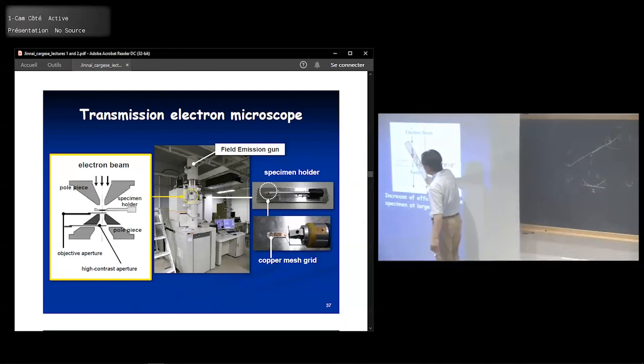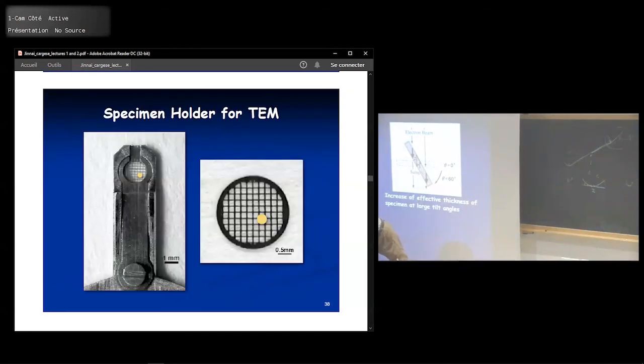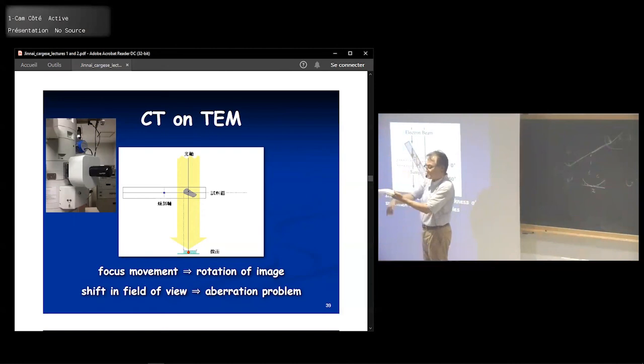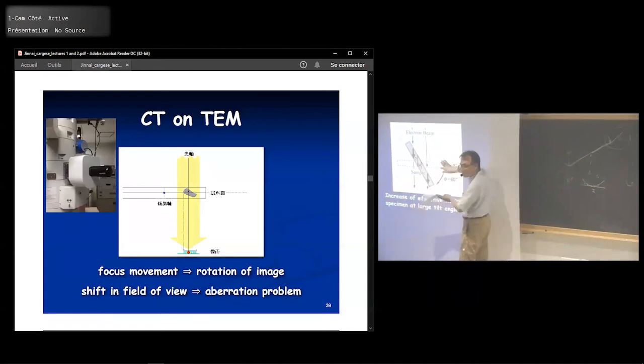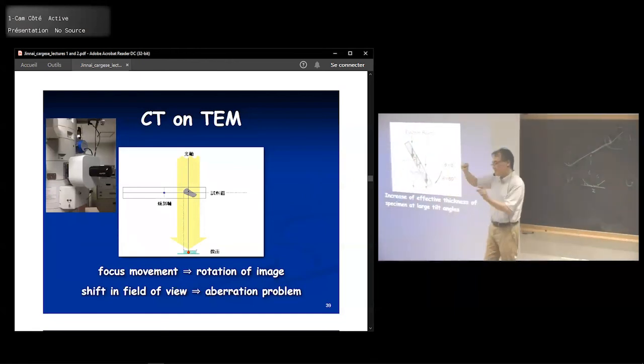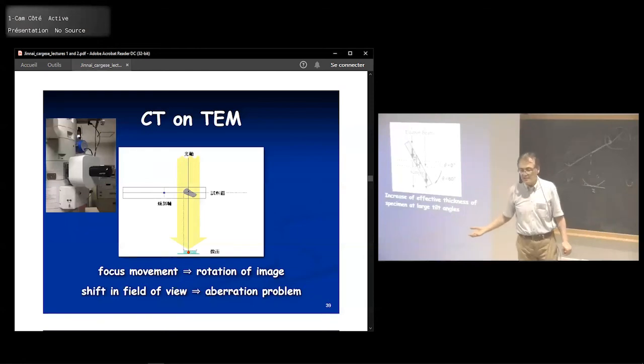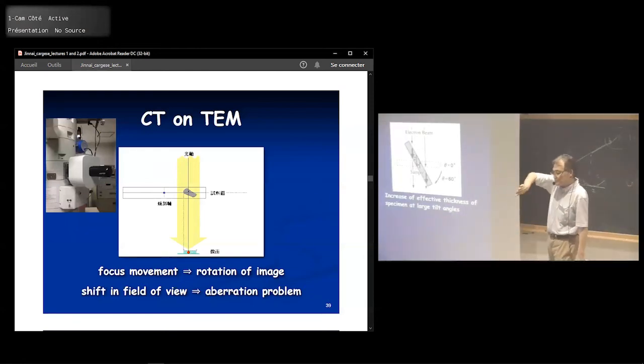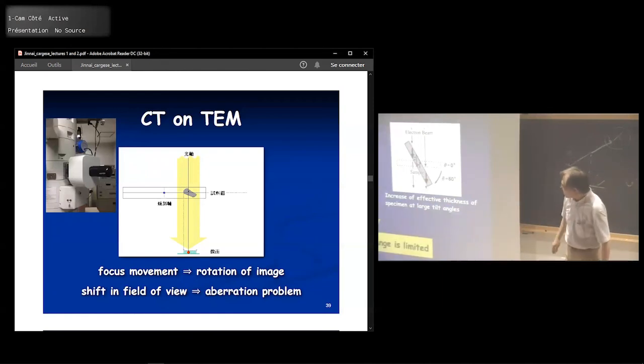And another problem is the sample. Like I said, the sample is microtomed. It's a thin sample, and then you have an electron going through, and take an image. You tilt the sample. Then the original thickness is, let's say, 100 nanometers. And as you tilt the sample up to 60 degrees, the effective thickness that the electron has to go through is going to be double. If you tilt up to 70 degrees, it's going to be triple. So although the initial thickness is 100 nanometers, at 60 degrees it's going to be 200 nanometers, and then 300 nanometers. As your thickness gets thicker and thicker, your image gets worse and worse. Those are the two limitations where we cannot tilt the sample up to 90 degrees. That causes a lot of problems.